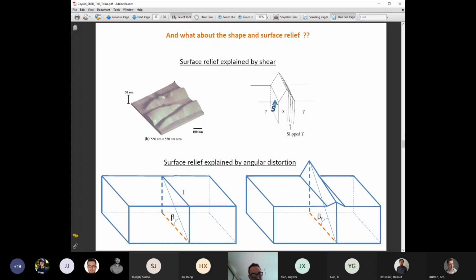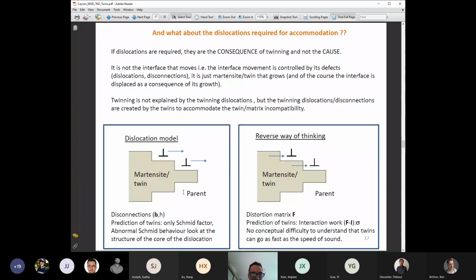And also, if I come back to this question, how can we explain that you can form twins or martensite? There is always this question that we need dislocation, that it's impossible energetically to form a shear immediately, instantaneously, and that we need dislocation. And I said, yes, I fully agree with the fact that we need dislocation, but it does not mean that the dislocation are the cause of the transformation. To me, they are the consequence of the transformation.